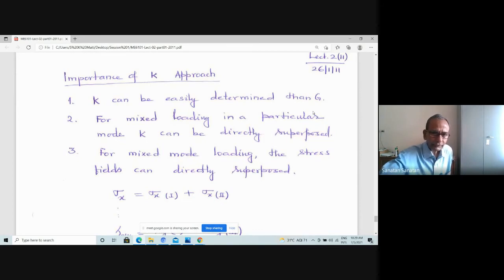Importance of the K approach. You see that first of all, this K stress intensity factor can be easily determined than G, which is difficult to calculate. So that was another stumbling block in applying the strain energy release rate concept. And for mixed mode loading, the solution for K can also be easily obtained, and therefore that also made it easy to apply the stress intensity factor approach to understand mixed mode problems.